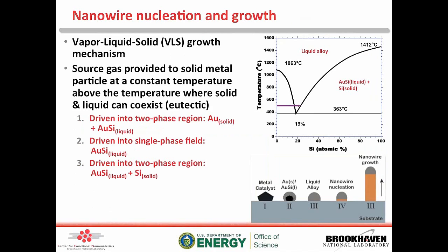The idea with nanowire nucleation and growth is that basically this vapor liquid solid growth mechanism works as follows. Generally, you'll start off with a small nanoparticle catalyst, shown here in step 1. You can bring the sample to an elevated temperature, and then you introduce a source gas that allows you to provide the growing material to the system. Basically, the source gas is catalytically decomposed by the catalyst and gradually incorporates into the material, eventually liquefying this alloy.